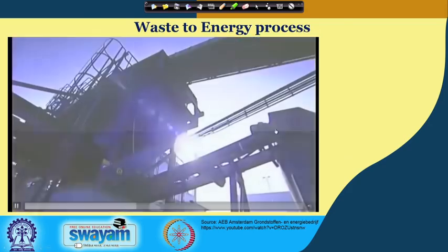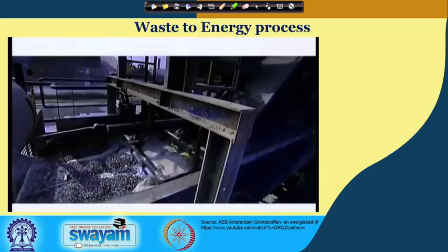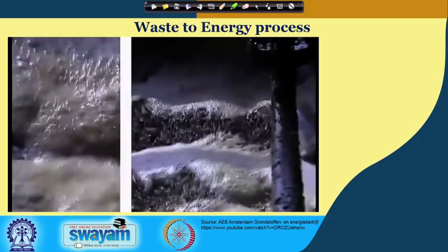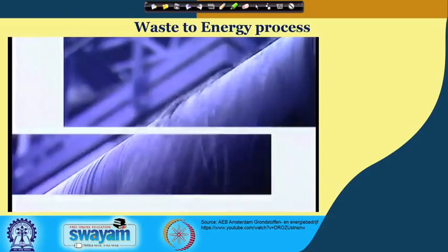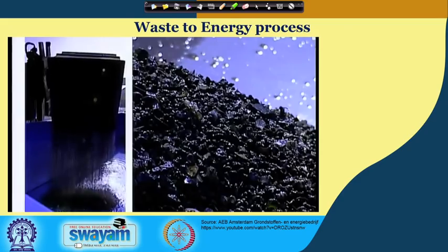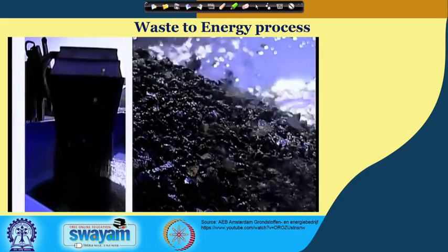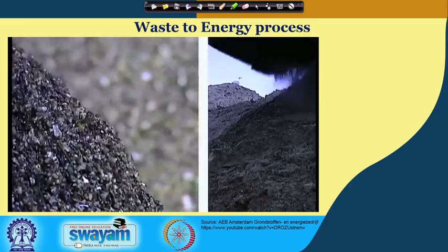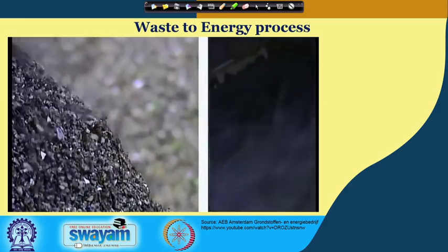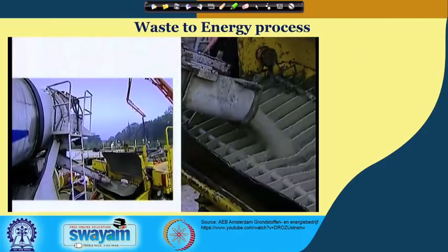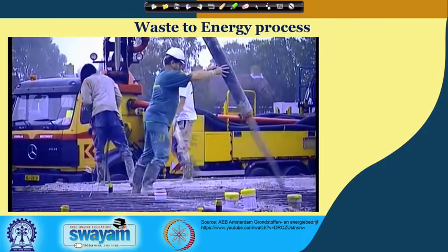Technology developed together with Delft University of Technology is used to wash and recover metals from the bottom ash. Large amounts of iron and non-ferrous metals such as aluminium and copper, are returned to the scrap metal trade for recycling. The rest is cleaned further until clean sand and a stony granulate remain. High-quality building materials which are used, for example, in concrete and asphalt.